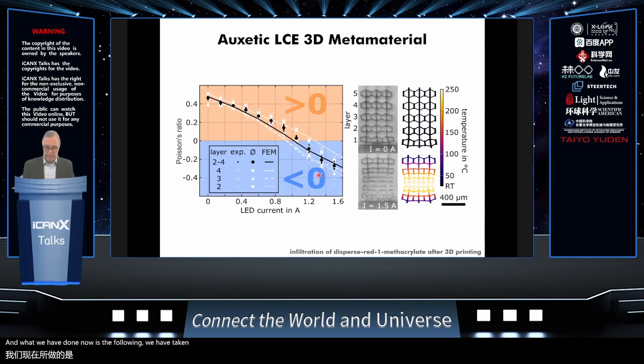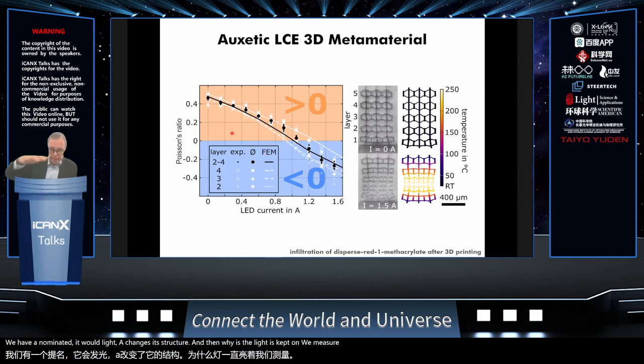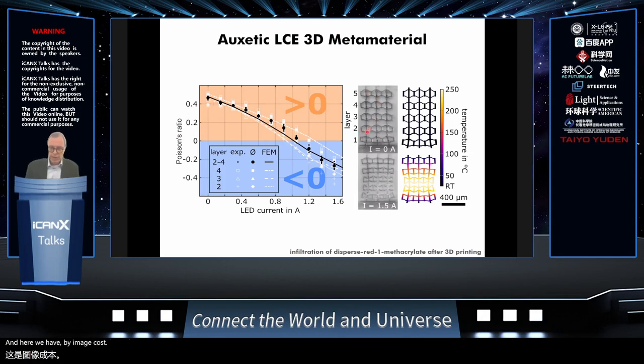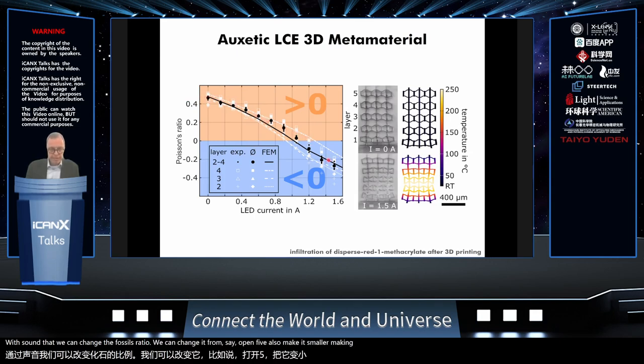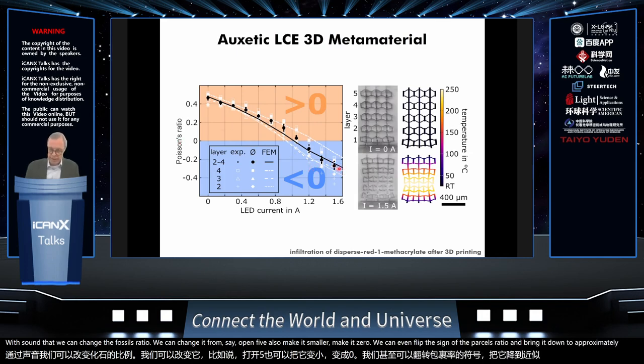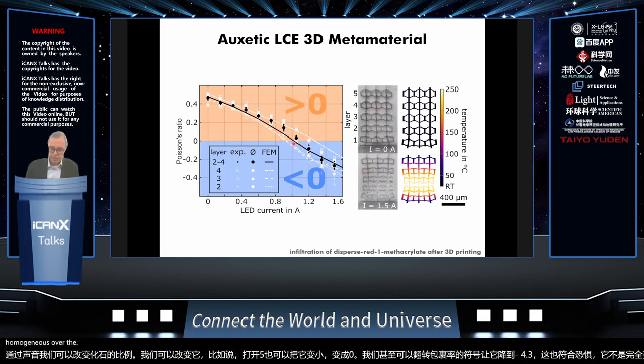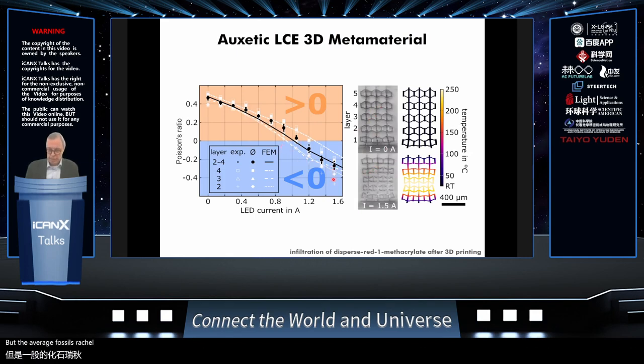And what we have done now is the following. We have taken the structure, we have illuminated it with light, it changes its structure. And then while the light is kept on, we measure in a mechanical probe station the mechanical properties. And here we have, by image cross-correlation analysis, you can see two images here as examples. We have found that we can change the Poisson's ratio. We can change it from, say, 0.5 or so, make it smaller, make it 0. We can even flip the sign of the Poisson's ratio and bring it down to approximately minus 0.3 or so, in agreement with theory.